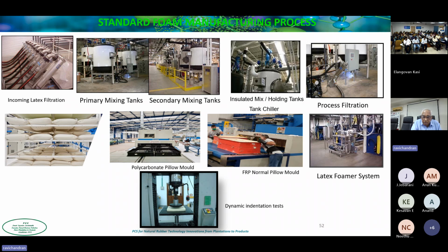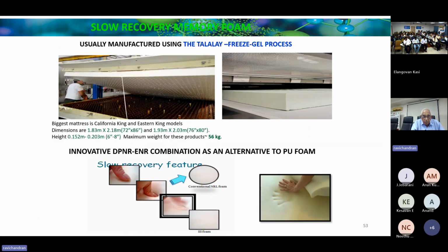On the left-hand side, the black molds are made out of polycarbonate. We first started using polycarbonate, but found that because of the radio frequency, there was cracking and the life was not enough, but FRP molds are now working very well. After we make the latex pillows, we have to keep them and mature them for about 14 days before they're ready to go out into the market.